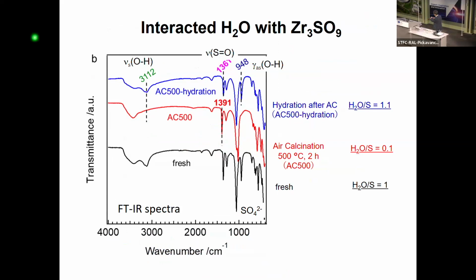This is the IR spectrum analysis. And these are fresh samples. You can see sharp, clear absorbance bands of IR. And this one is due to the stretching vibration mode of S=O. And after calcination, meaning removal of the water, you can observe the shift of this band from this number to this number. At the same time, we observe disappearance of the water absorption spectra. After adding water again, you observe the same IR band as observed in these fresh samples.